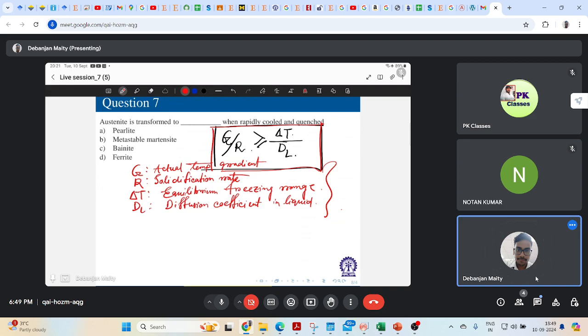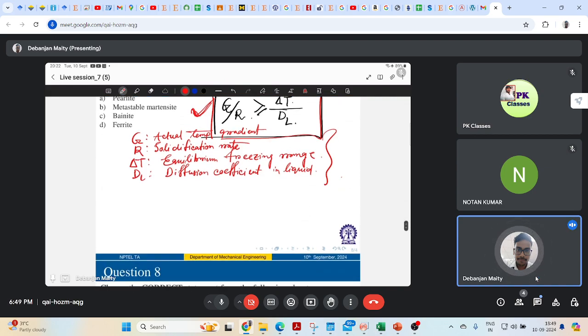You'll either have some columnar structure or some equiaxed structure. Now, if we concentrate on this equation, G by R is greater than or equal to delta T by dL, what can we infer from it? It will tell me a few things, I'll note it down. If your temperature gradient is higher and your growth rate is lower, what will happen? It will be easier for a planar interface to be stable, right?